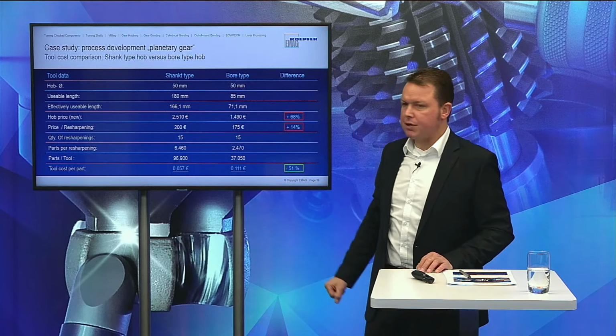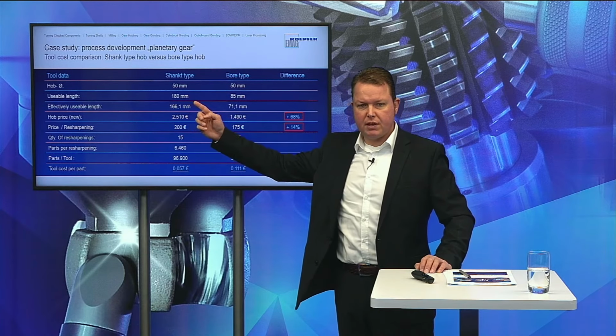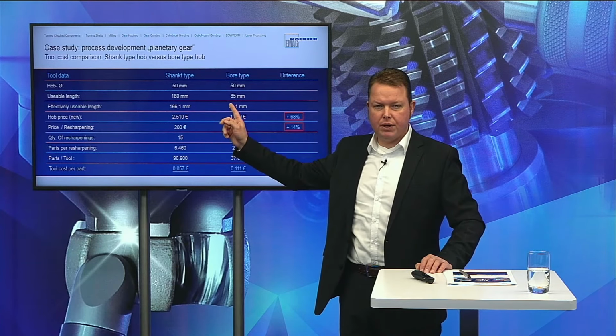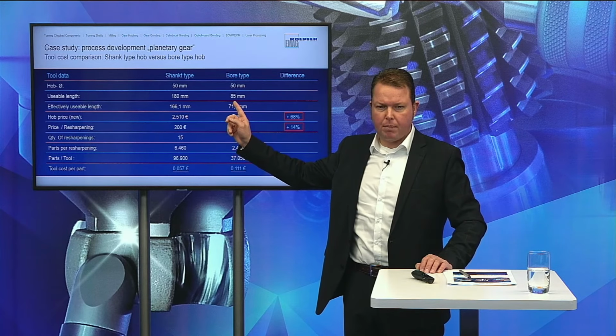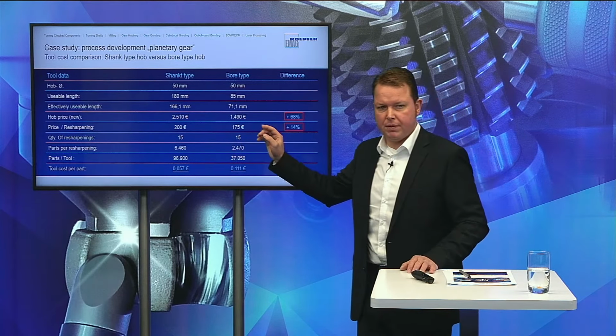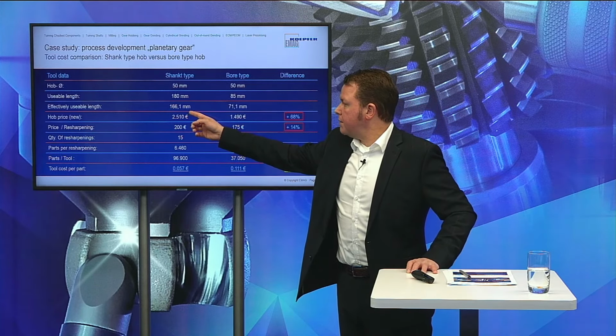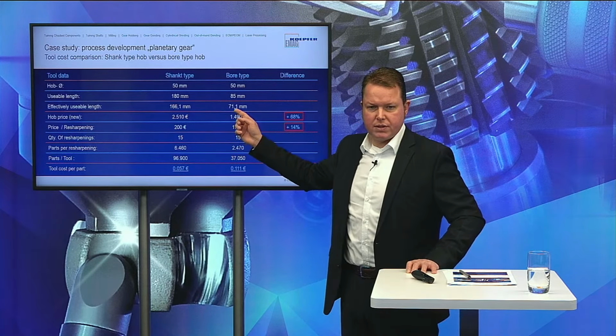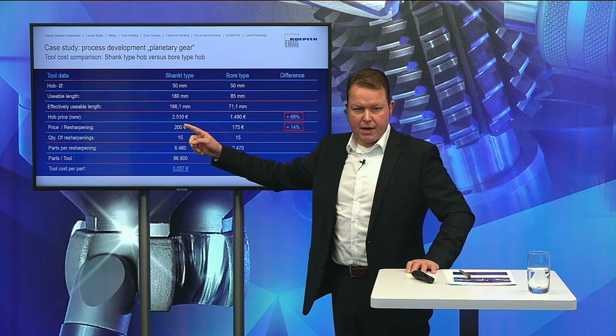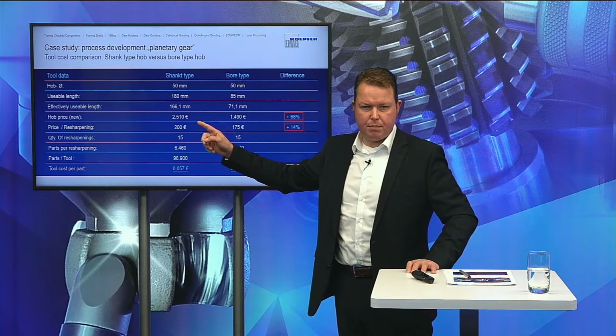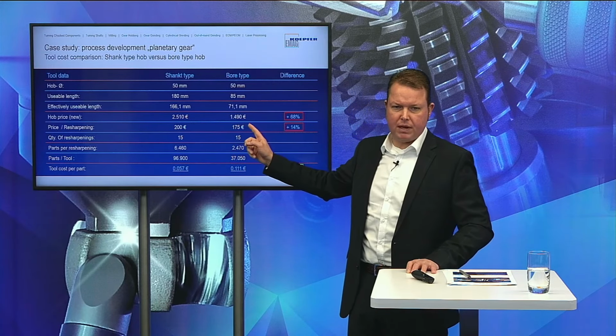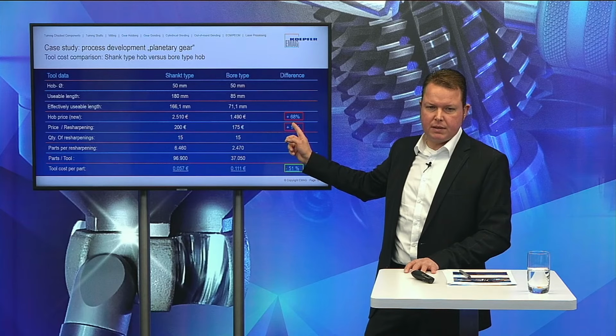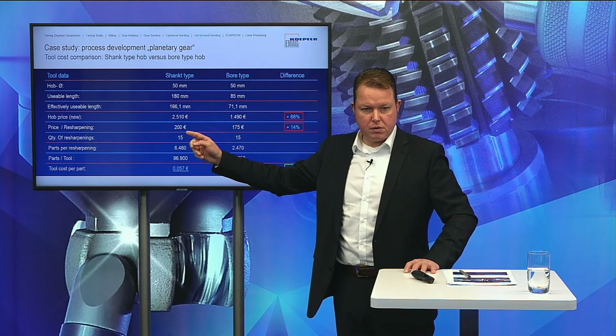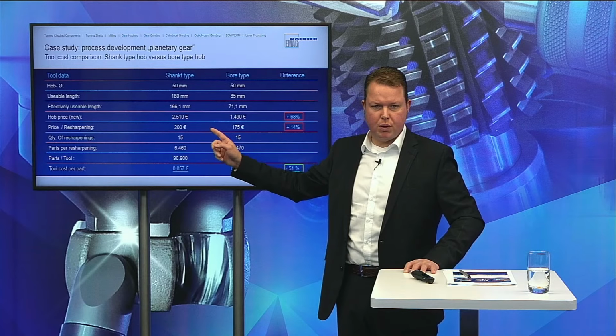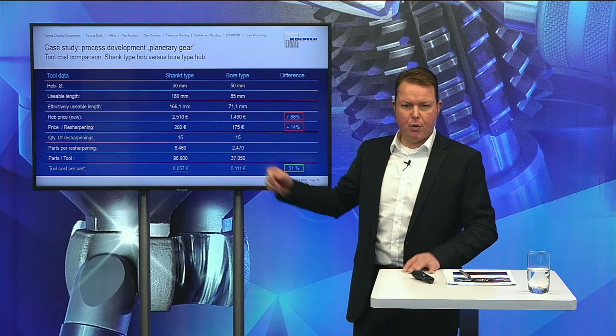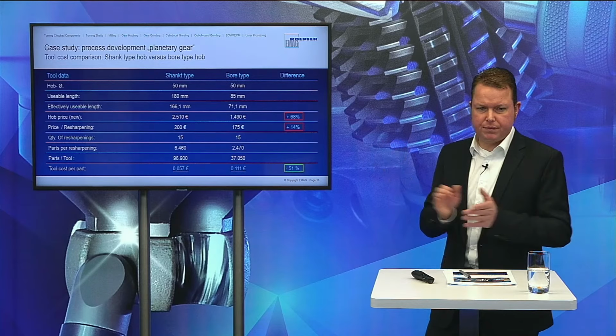have 50 millimeter diameter. The usable length of the shank type hob is 180 in this case, only 85 in case of the bore type hob, and this is already quite a long bore type hob, by the way. Effective shifting range 166 versus 71. Purchasing price is 2,500 for the shank type hob, only 1,500 for the bore type hob, so there's a difference of 70%. The resharpening cost is also higher in case of the shank type hob, 200 versus 175.